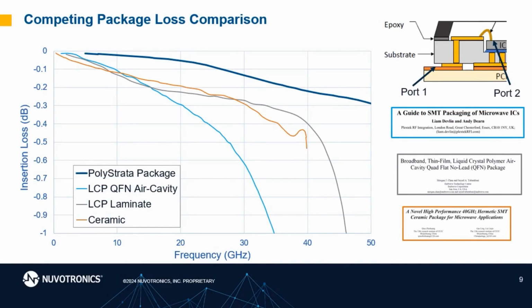In this slide, I've collected some publications on three other technologies used for surface mount RF packages. These are all QFN style packages, air cavity, and you can see the general insertion loss plotted by frequency, and the performance is above 0.5 dB up to 40 gigahertz. But really, depending on the technology chosen, there's a dramatic drop off above 40, and depending on your application, even 0.5 dB insertion loss is not acceptable.